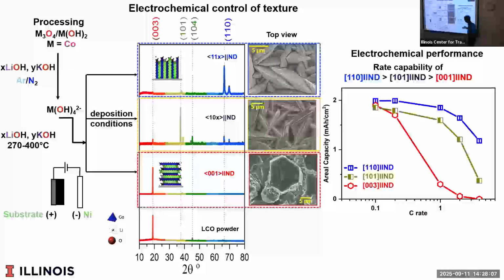These are scanning electron microscope images. Basically, we're looking at it, and I put this up here because it turns out that the lithium goes really fast through these little sharp edges you see. Imagine a book. This is like the book standing up and the lithium goes between the pages. Here's the same book turned this way and the lithium can't go through. So this really depends on the details of how my crystals are oriented. If my crystal's the wrong direction, it does not work.